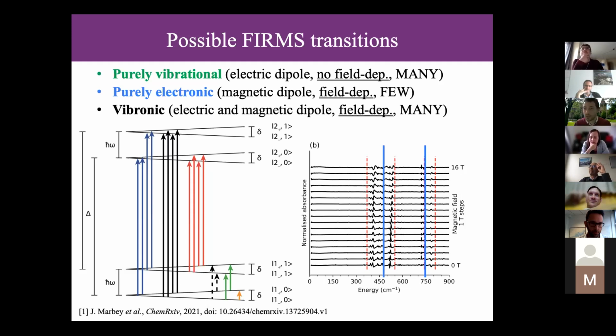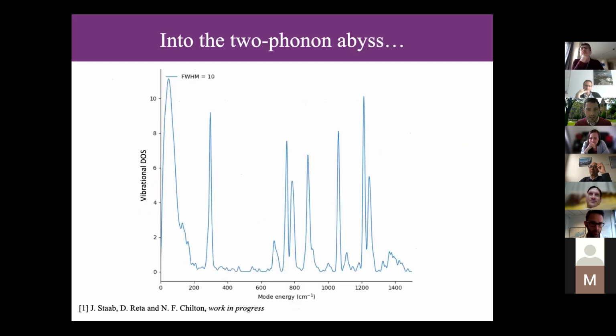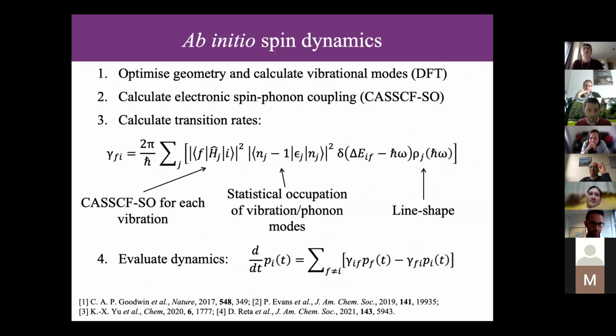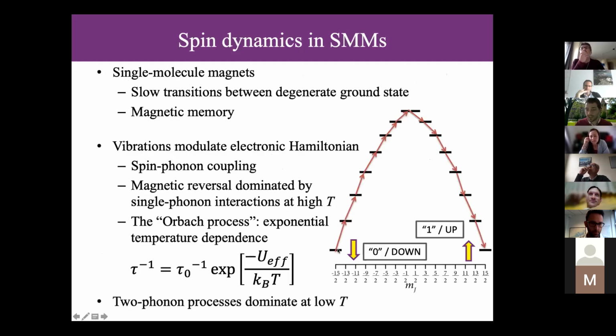That's true, yes. So we're now talking about different parts of the expression for single phonon transition rates, which is this. So if your coupling, this Hamiltonian matrix element, is 0, it doesn't matter how close your energy is, you're still going to have a 0, right? Fine. But yes, it must couple, it must link the two states, but it also must be the right energy. And it must be the right energy because you are literally absorbing that vibrational energy to make the transition. So you're essentially going from a state where you have some occupation of a vibrational mode up here, and then you're reducing the vibrational occupation by 1 whilst you excite an electronic transition. That's what this says. You go up in electronic excitation and you lose a quantum of vibration for that mode.